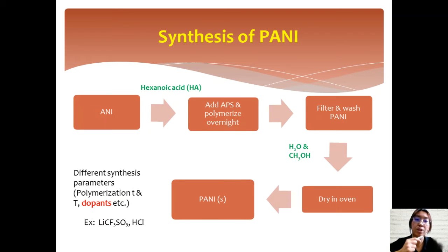And then it will dry in the oven for another 24 hours. Lastly, the sample can be collected in solid form. Different synthesis parameters such as dopants, the polymerization time and temperatures will be varied in order to form different morphologies. The dopants chosen in this study are lithium triflate and hydrochloric acid.